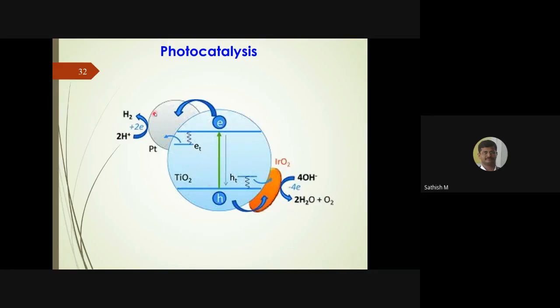So people introduce some metal here, which we call a co-catalyst. Since this is the main catalyst, this is a co-catalyst. The role of this co-catalyst is to attract the electron produced in the conduction band. For example, if the electron comes here, and the reduction of H+ to hydrogen takes time, that means the rate of this reaction is slow, and the recombination will be very high. To avoid this, we have another catalyst, so this electron is transferred to it.